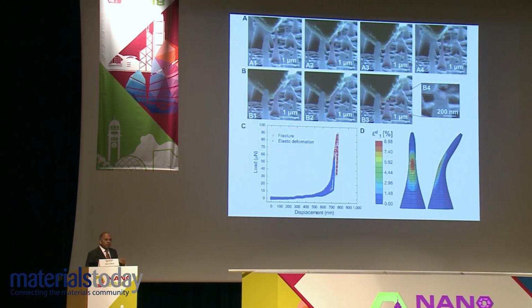So here is a series of still images from the videos that were taken in the experiment showing how the diamond deforms. This is in a single crystal. In the top row, as the indenter tip comes down and starts to deflect the diamond, you can see the needle tip being bent. And if you don't reach a critical threshold value of stress or force, but you retract the diamond tip, the needle goes back to its initial shape. And that's what happens in the top row. In the bottom row, if you do the same thing, but exceed the point at which fracture is initiated, you see the catastrophic fracture in the middle of the figure, in figure B3, where you see the diamond needle being catastrophically fractured. And you see the fracture surface in B4.